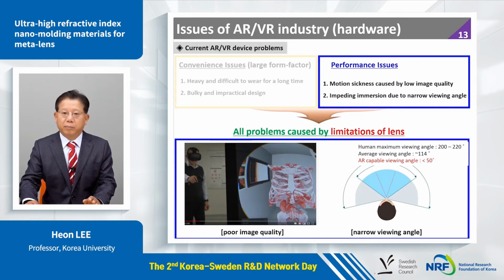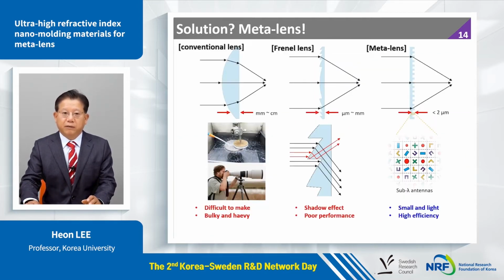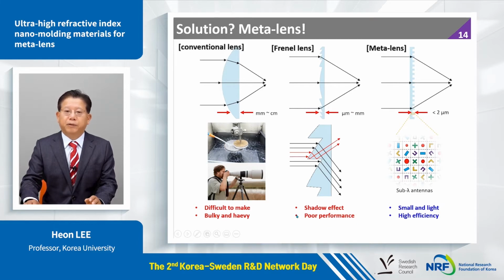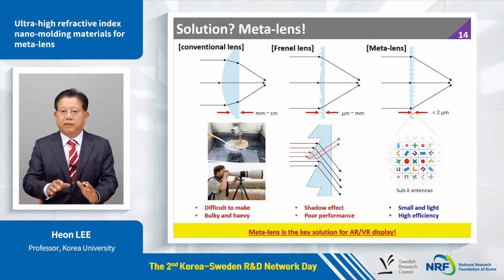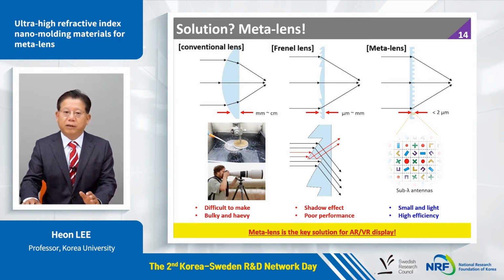If you can realize the metalens, you can shrink down its form factor, and you can increase the efficiency. So we can make some very nice, small, and highly efficient AR/VR devices. This is a conventional lens, which is on the millimeter scale. This is a Fresnel lens. It's much thinner, about hundreds of microns. However, it has poor performance. But if we can realize the metalens, we can scale down the thickness of the lens to as small as 2 micrometers. That means we can decrease its form factor by more than 1,000 times. So the metalens is the key solution for AR/VR displays.